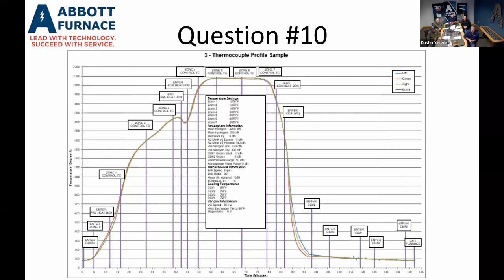Usually what happens is the glow bars are starting to wear a little bit and you may not be able to hold temperature in that zone. Or the product is heavier and somebody increased the belt speed or put a lot more weight on the belt, and the zone won't hold temperature. That can get into a lot of troubleshooting as far as electrical, to make sure that zone is putting out the power it needs to heat that part up to that temperature. So temperature deviation has two different aspects that you can look at.